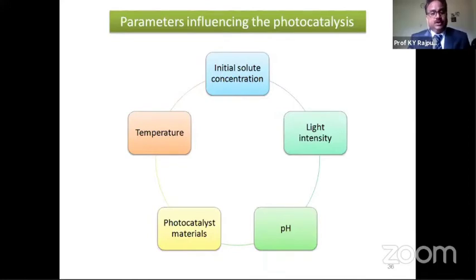If it is not, then you should do a serial dilution. The material of the photocatalyst matters, whether it is TiO2 or zinc oxide, or doped zinc oxide, or a composite, or iron oxide, or something else, or a ternary compound. Temperature also is very important. The temperature should be optimal.